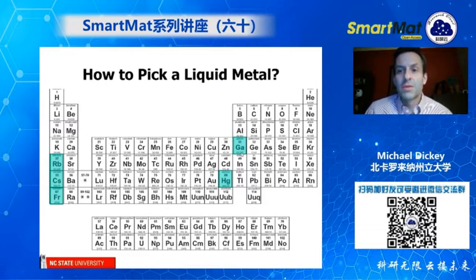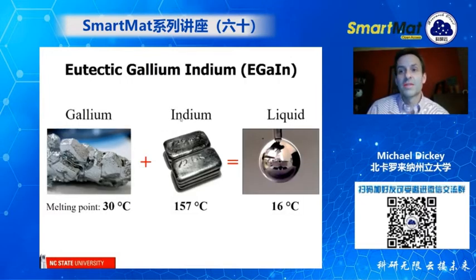So gallium technically melts at 30 degrees Celsius. So that's a little bit above room temperature. This is a picture of a crystal of gallium. And if you add in other metals like indium, for example, you can depress the melting point to below room temperature. So when you mix these two things together, you get a liquid. And the composition we use is called the eutectic gallium indium. And eutectic just means the composition with the lowest melting point. That's about 75% gallium.